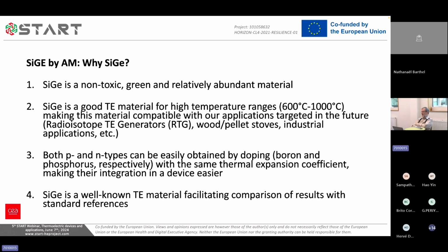One advantage is that both N and P materials can be produced from the same raw material with different doping. And the advantage is that you get the same expansion coefficient. So that's really an advantage with silicon germanium. And it's a quite well known thermoelectric material, meaning that with our 3D printing trials, we can always compare and benchmark with other publications, other works.